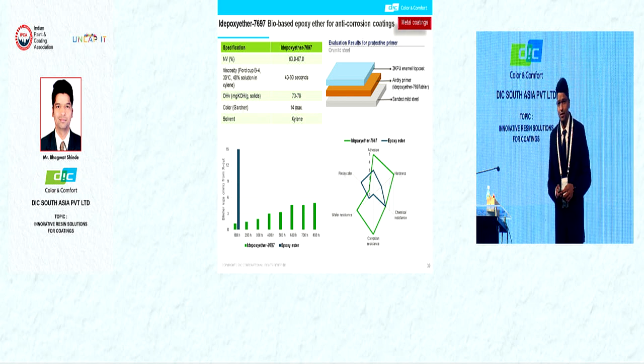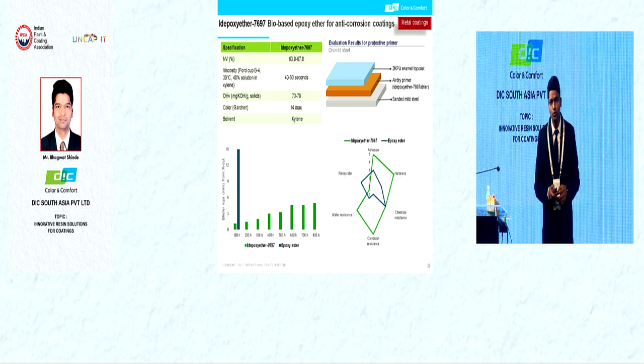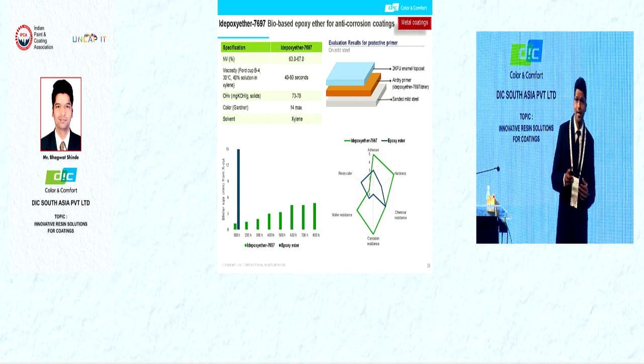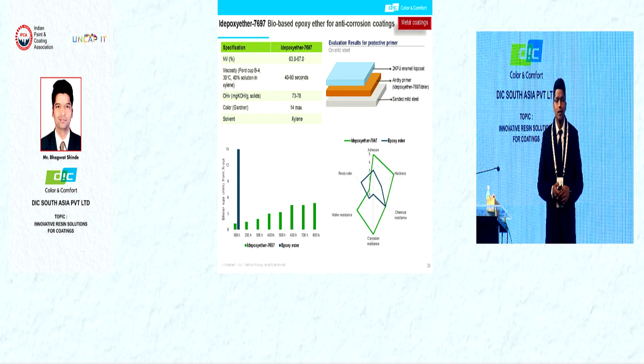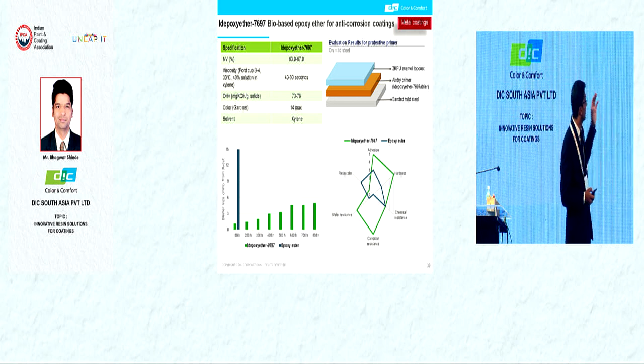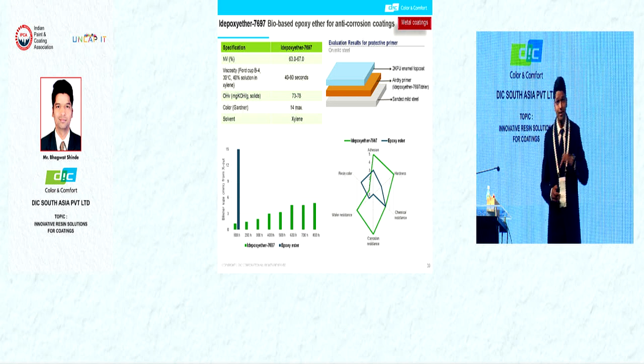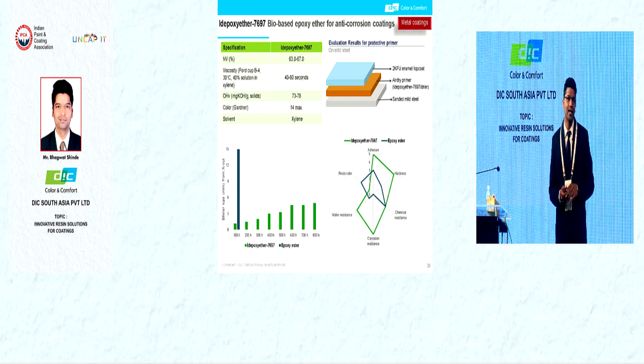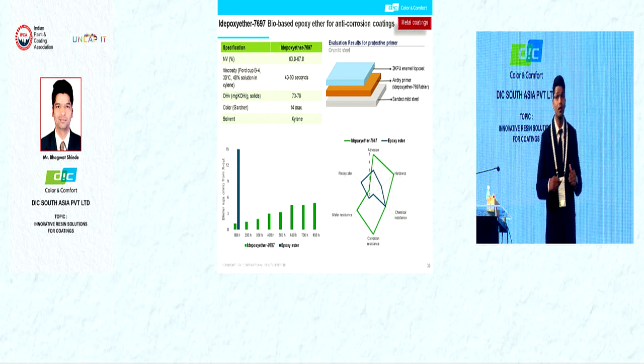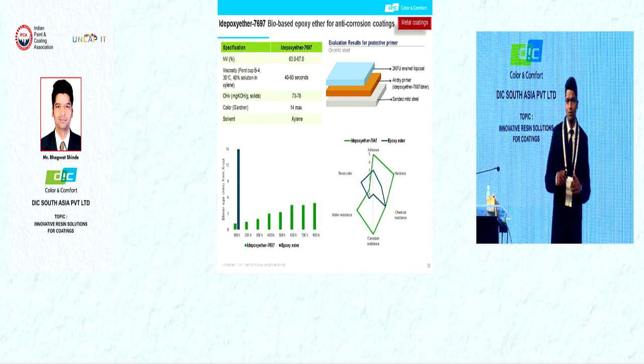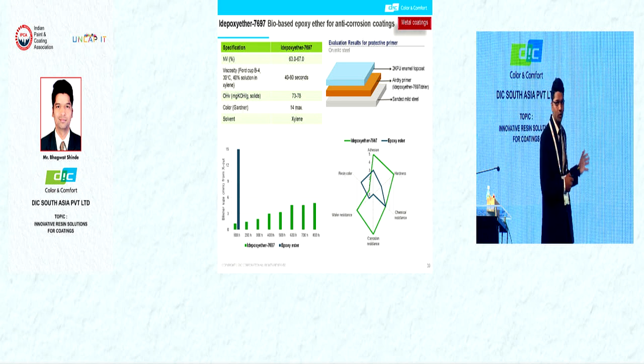This product we recommend for the anti-corrosive coating for DTM as well as base primer. This product, you can see, we have recommended as an epoxy ether, that product having the ether linkages, and ether linkages show a good water resistance, and due to this, good corrosion resistance.